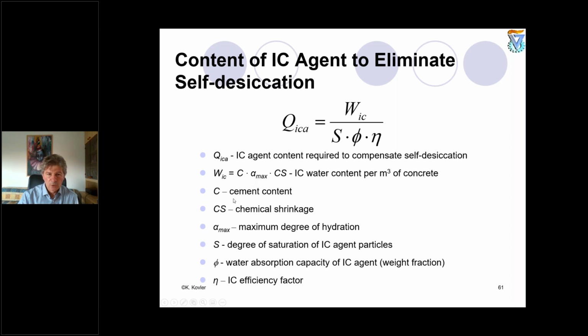All calculations are, of course, made for 1 cubic meter of concrete. C in this formula is cement content. CS, as in the previous slide, designates chemical shrinkage. Alpha is the maximum degree of hydration expected. And S, and this is very important to know, is the degree of saturation, because sometimes we have not fully saturated particles of internal curing agent.